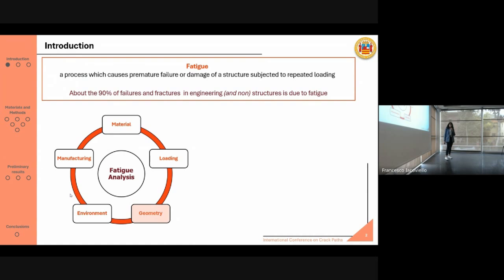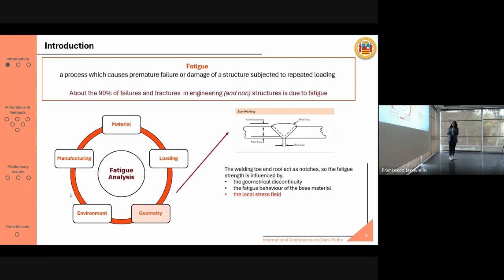So when we talk about components, for example welded joints, the geometry plays a very important role, because we know that the welding toe, in case of welded joints, and root act as notches. So the fatigue performance is influenced by the geometrical discontinuity represented by the welding toe, the fatigue behavior of the base material, and the local stress or strain field. That's why local approaches are appealing.